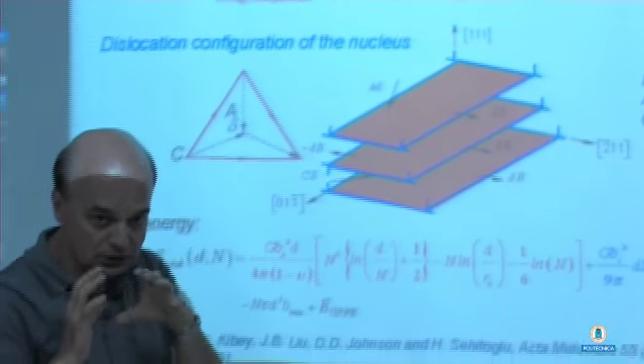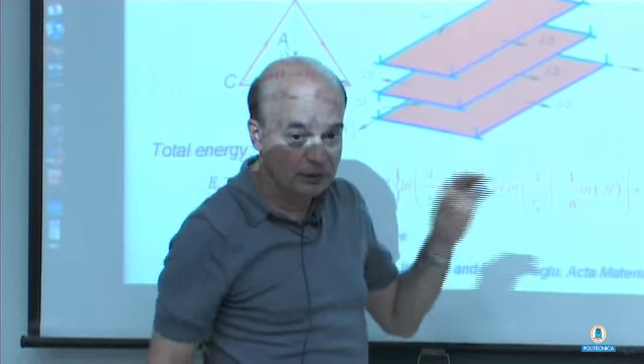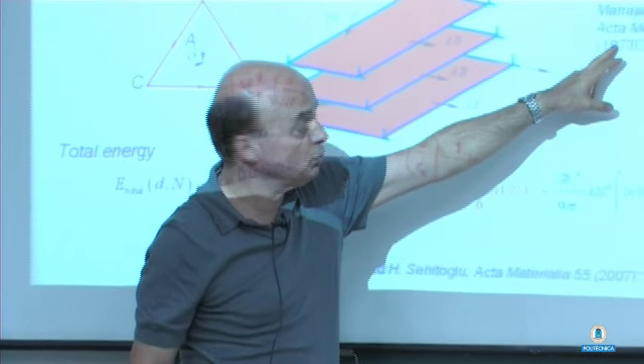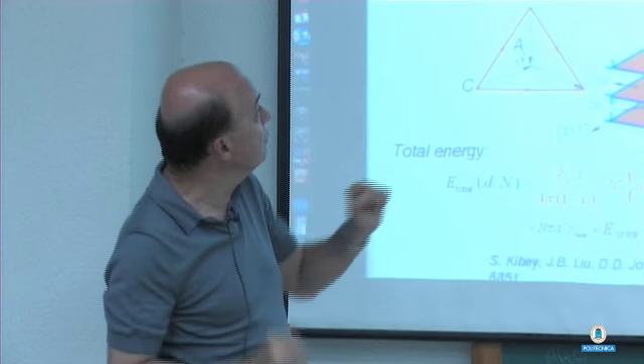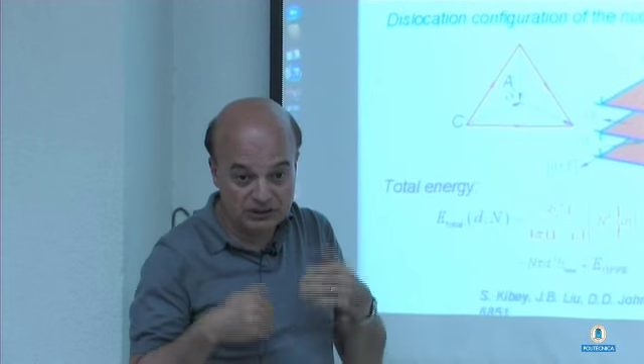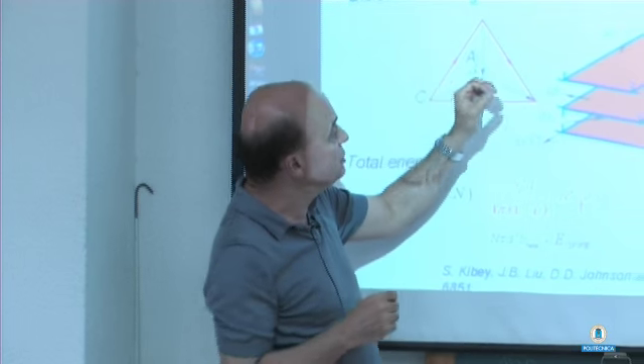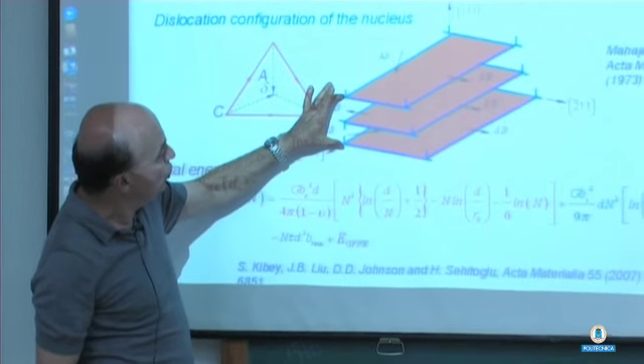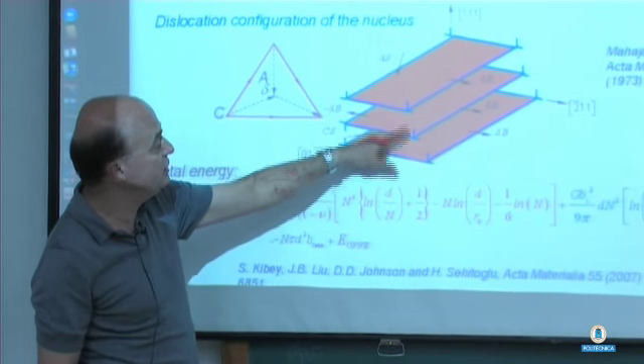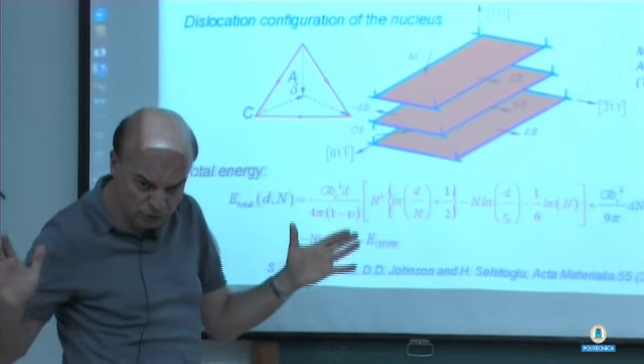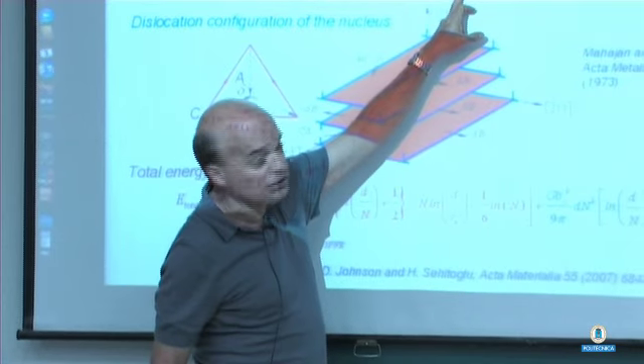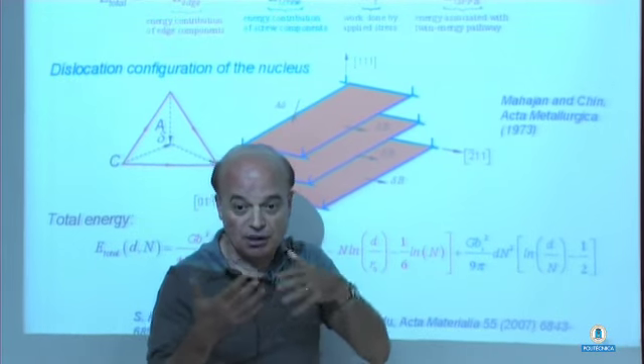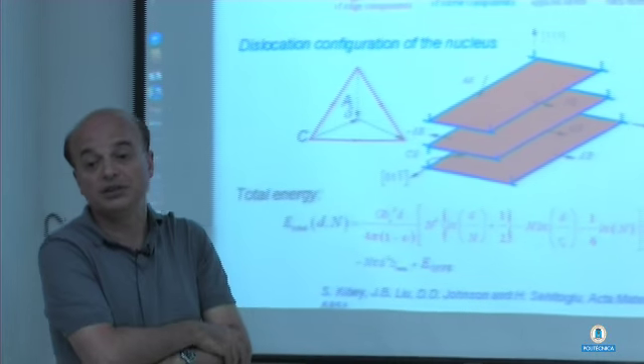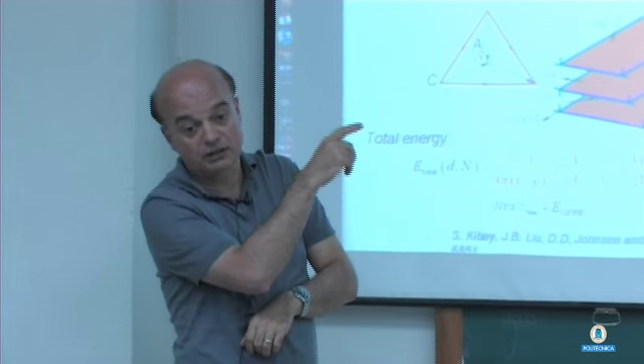This twin nucleation has been observed as a three-layer twin with transmission electron microscope, and has also been postulated by Mahajan and Chin in 1973. What we have now is the following. We have a total energy, which is a combination of the elastic energy associated with these dislocations that bound the twin nucleus, work done by applied shear stress, which we know, and then we have to overcome the energy associated with the twin energy pathway. That's the generalized plane fault energy.